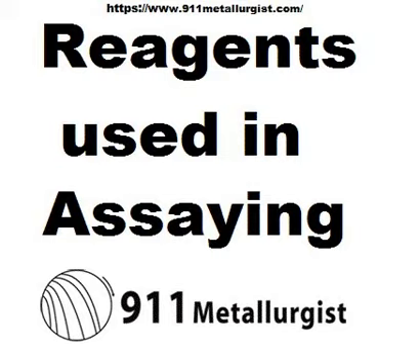It has no action on the following metals: gold, platinum, arsenic and mercury. It very slightly attacks antimony, bismuth, lead, silver and copper. Tin is more soluble in it, but with difficulty, whilst iron, zinc, nickel, cobalt, cadmium and aluminium easily dissolve with evolution of hydrogen and the formation of the lower chloride, if the metal forms more than one class of salts. All the metallic oxides, except a few of the native and rarer oxides, are dissolved by it, with the formation of chlorides of the metal and water.